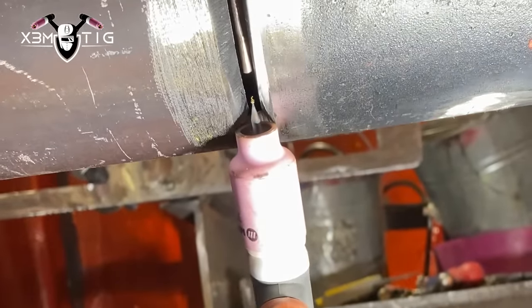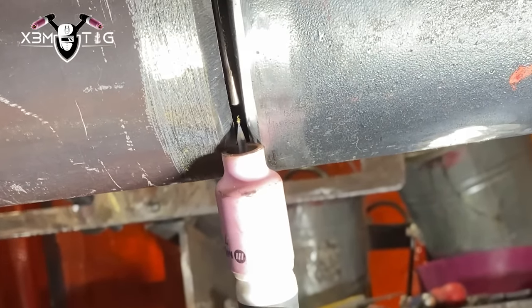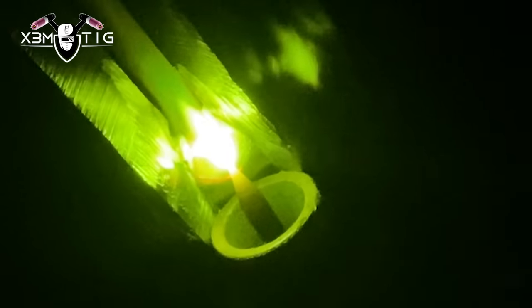Same thing on the bottom, grind stop starts, that start point. When you're going, wait, start melting, get ready with that rod close. You want to see it, and once it started, once you get that puddle liquid, just add that rod and just keep it connected. Same thing on this side, nine or three o'clock depends on what side you want. You can then stop and switch to dipping technique and pull that rod outside.